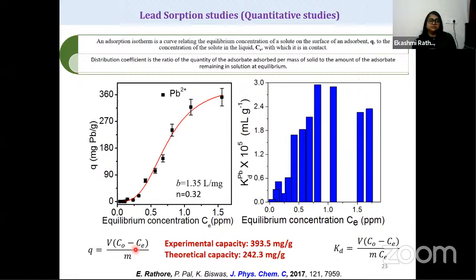With the help of this capacity formula, where C naught is the initial concentration, C is the final concentration, V is the volume, which is 10 ml, and M is the 10 milligrams of sample which we have used, we calculated these values, and we found out that the capacity is 393.5 milligrams per gram. What it means is that 1 gram of the material can capture 393.5 milligrams of lead.